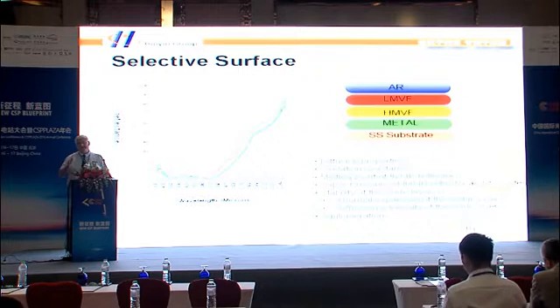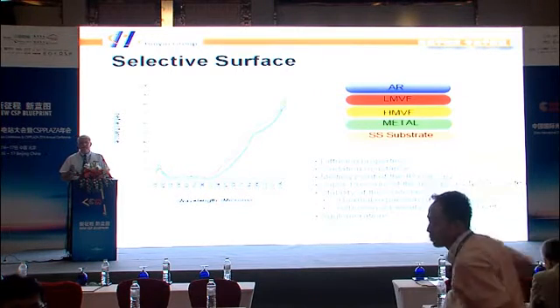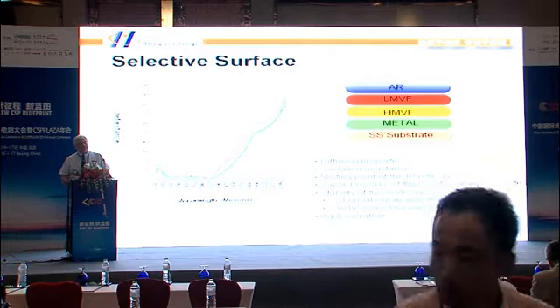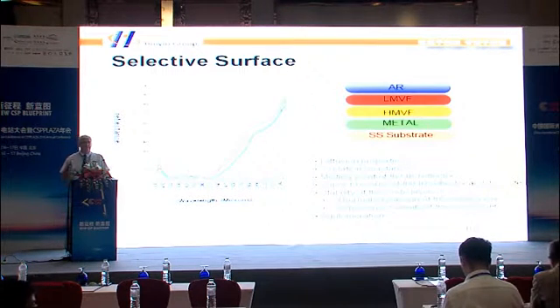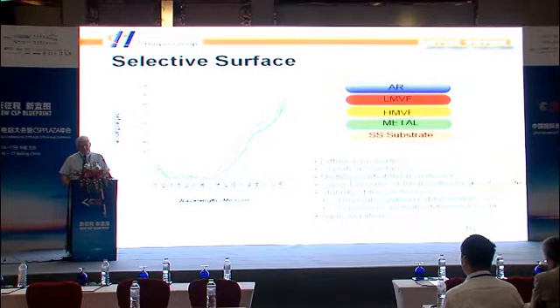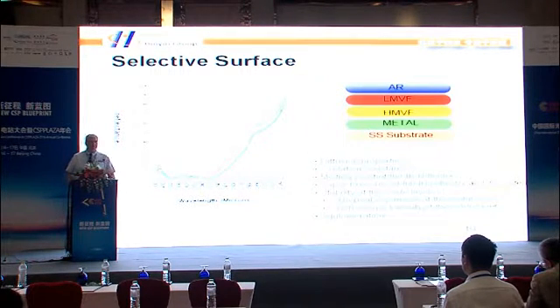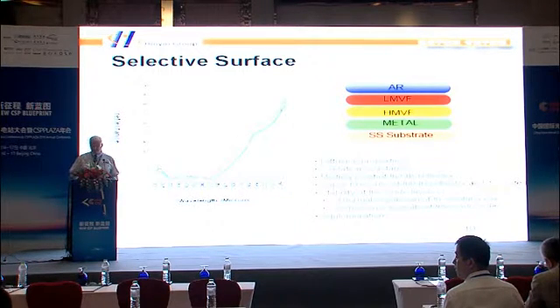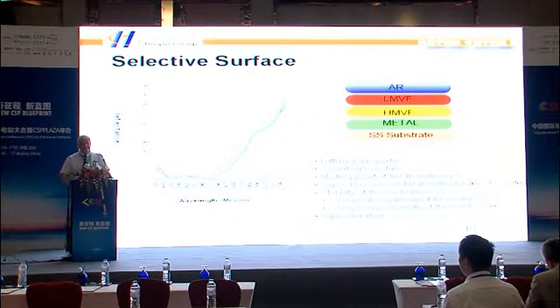The total layer thickness of such a stack is only 300 nanometers, and some of these coatings are something like 5 nanometers thick, so it's extremely, extremely thin. One of the problems is to block diffusion, to make sure that all these layers don't start to mix together. We do that with diffusion barriers that we put in between all of these layers. So the core of the technology lies in the use of diffusion barriers that block diffusion going through the other layers.